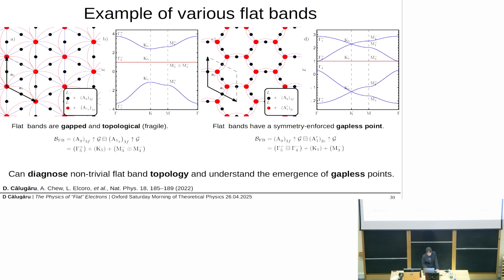To cut a long story short, on the left-hand side, I can go ahead, use topological quantum chemistry, once again, not do a single calculation, and show that the flat band must be topologically non-trivial. And on the right-hand side, using the same algorithmic prescription, I can do the same and show that the flat band has a symmetry-protected gapless point at the gamma point, right? So it touches the dispersive band at the gamma point.